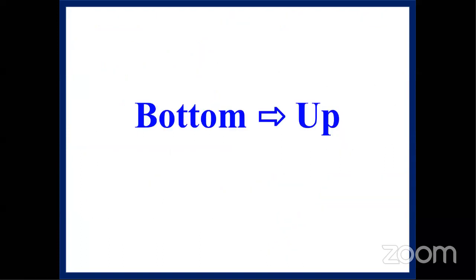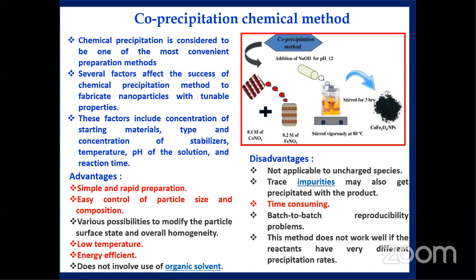And next is the bottom-up process. I am going to explain a few methods of how we can prepare nanostructure material. You can see here, this is the co-precipitation chemical method. Chemical precipitation is one of the simplest and most convenient methods. We can control the concentration of the precursors, temperature, pH of the solution, and reaction time. Here I mention cobalt ferrite nanoparticles prepared by this co-precipitation method. There are two precursors: cobalt nitrate and iron nitrate, mixed together with a suitable solvent with the help of a magnetic stirrer. The solution is stirred vigorously at 80 degrees Celsius.